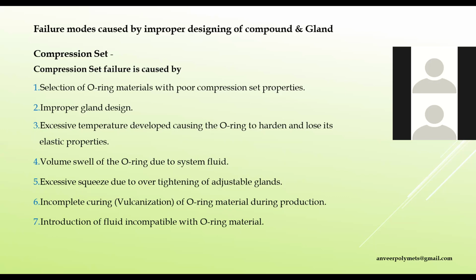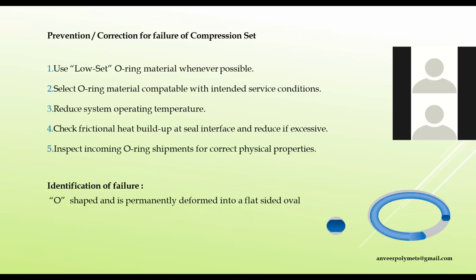Incomplete curing of O-ring material during production also leads to compression set failure. Then the introduction of fluid incompatible with the O-ring material. Then preventions. We can prevent this by choosing low-set O-ring materials, by selecting O-ring material which is compatible with service conditions. We can reduce system operating temperature. We can check the frictional heat buildup at the seal interface and reduce it if excessive heat is generated. We can inspect the incoming O-ring shipment for the correct physical properties.